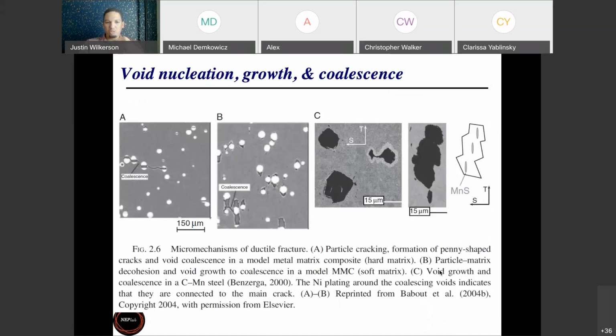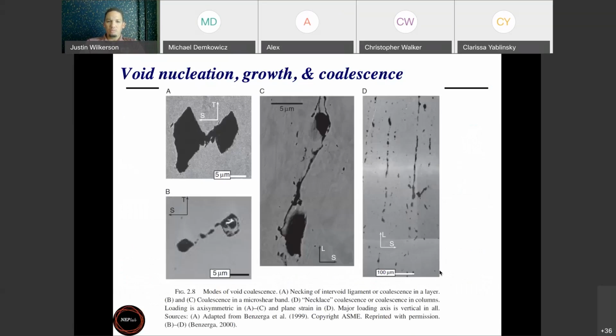And like I already mentioned earlier, these voids tend to nucleate at some kind of other material defect, be that second phase particles or grain boundaries, triple junctions, something like that tends to be the void nucleation sites in most metals. And then this is showing a few different coalescence modes, ways that two voids can link up and lose load carrying capacity. So there's a lot of complexity that's going on in spall failure.